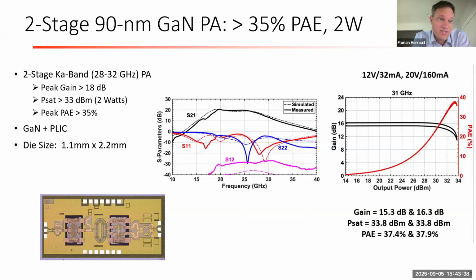Building on that, we developed a 2-stage design at Ka-band, achieving over 18 dB of peak gain, over 2 watts of output power, and efficiency of greater than 35% at the probe station, right? So measured with RF probes on the chuck with no extra cooling. Again, 2 chiplets in a pseudolithIC wafer with a die size of about 1 by 2 millimeter. And yeah, excellent results, right? This starts to be fairly competitive at Ka-band in the 2-watt class amplifiers with high efficiency. What's unique, obviously, is that on the long-term roadmap, a lot of the DC biasing and power management will be done in the CMOS platform, and therefore we can use different voltages at the gates in the final solution, while today, obviously, it's done with an external power supply.